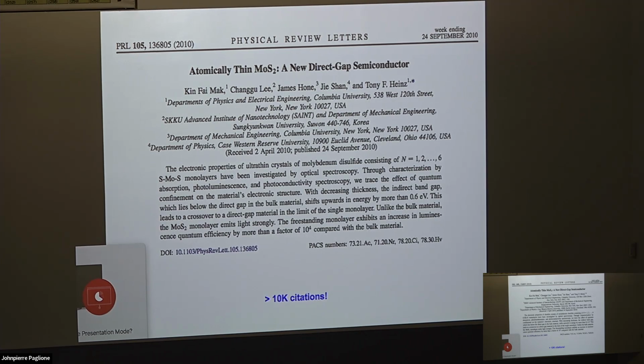single layers of molybdenum disulfide have a direct gap, whereas multi-layers have an indirect gap. This was an incredibly important result, because direct gap semiconductors are much more interesting for many applications, such as photovoltaics and so forth. Their efficiency in capturing photons is much higher. So this really was a big breakthrough.